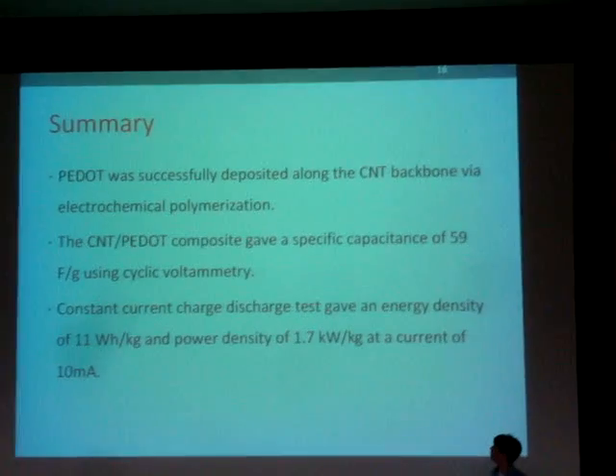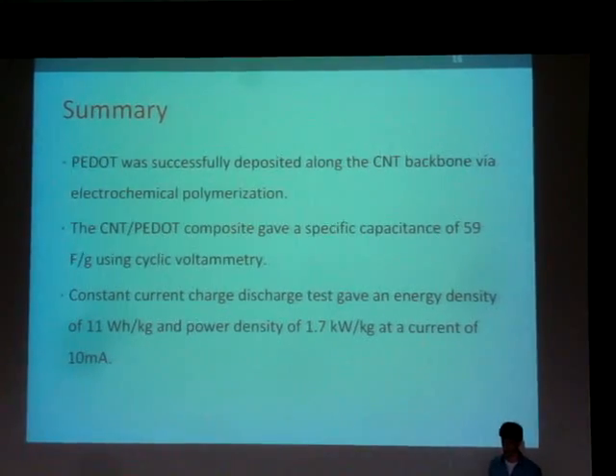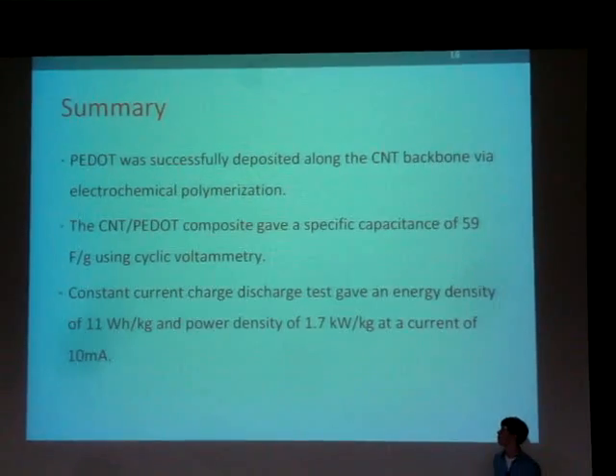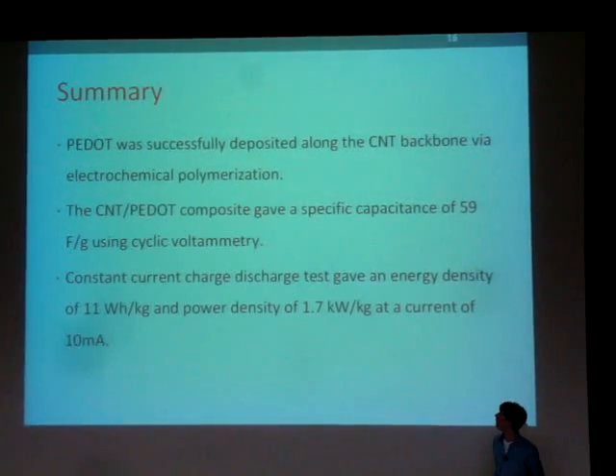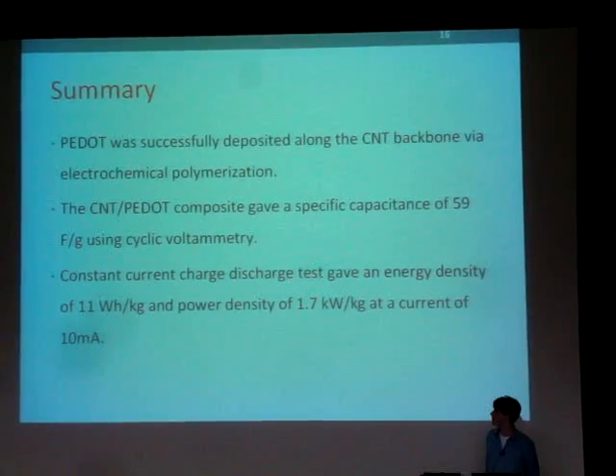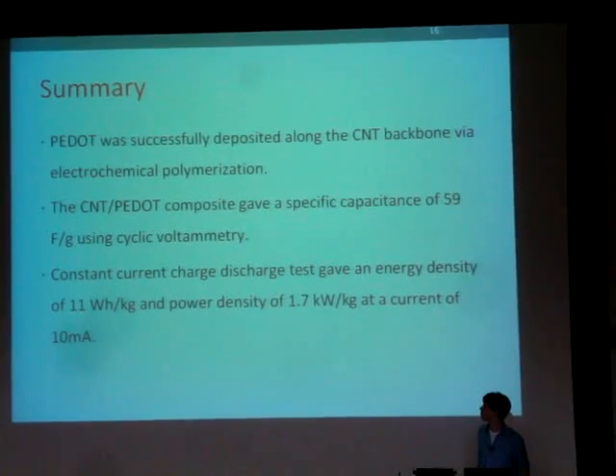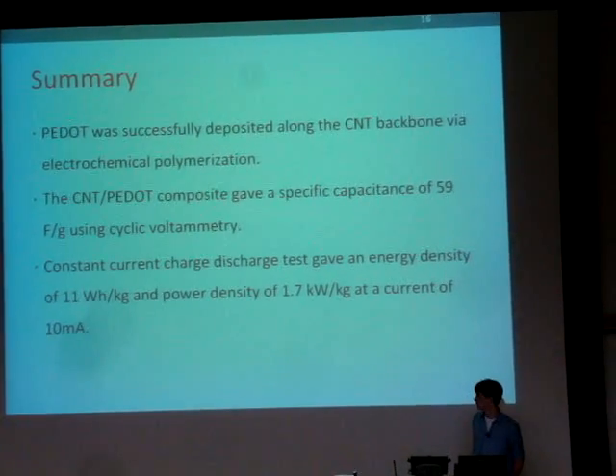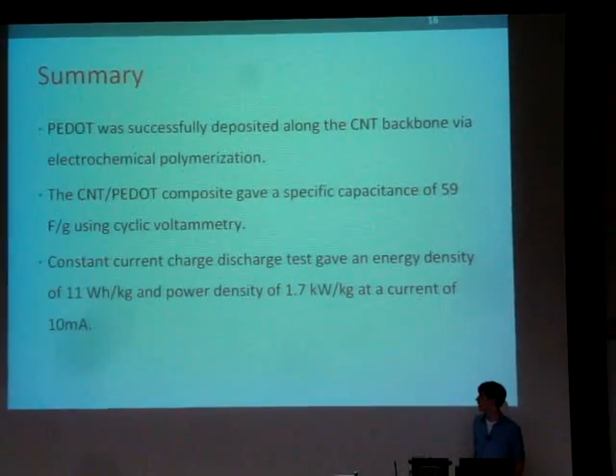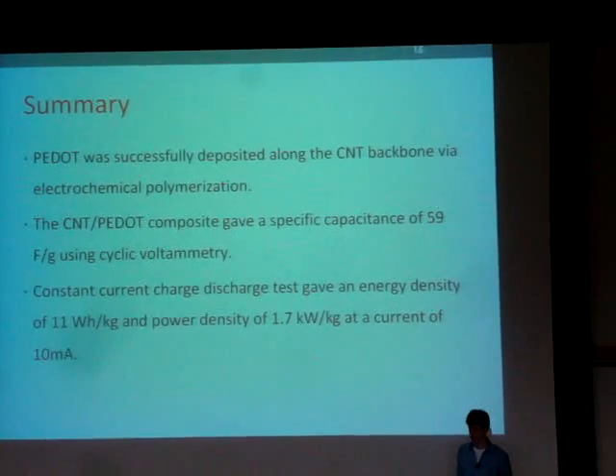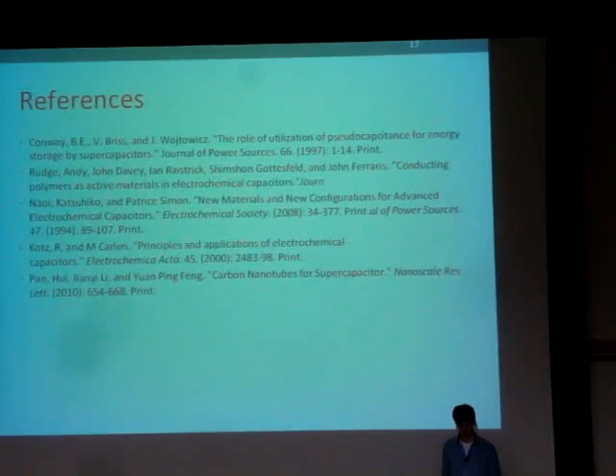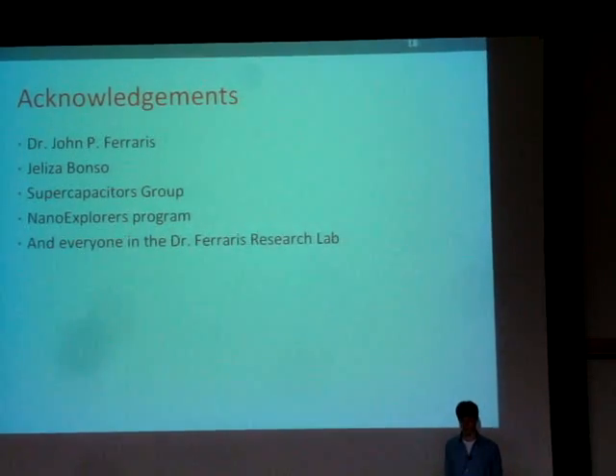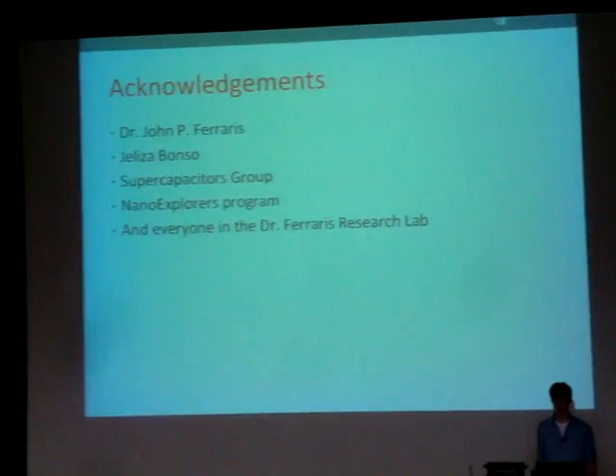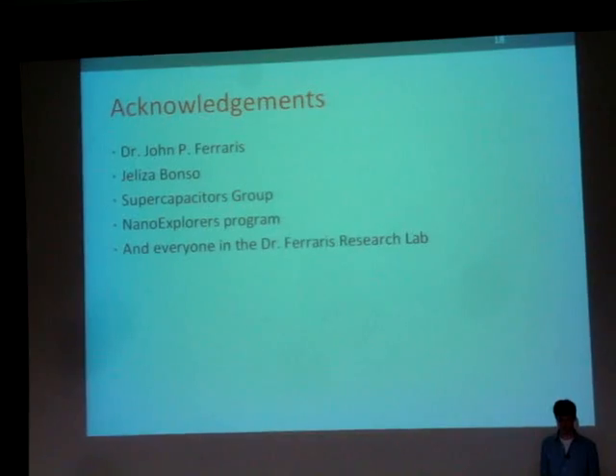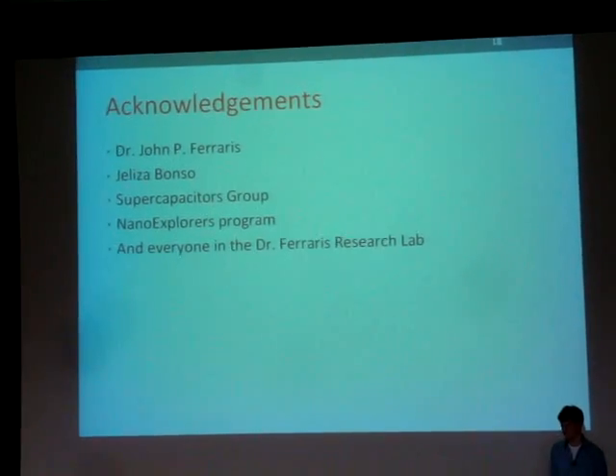So in summary, PEDOT was successfully electrodeposited onto the carbon nanotube backbone via electrochemical polymerization. The carbon nanotube composite gave us a specific capacitance of 59 farads per gram, and constant current charge-discharge test gave us an energy density of 11 watt-hours per kilogram, and a power density of 1.7 kilowatts per kilogram at a current of 10 milliamps. And I'd like to thank Dr. John P. Ferraris, my mentor Jaleesa Bonzo, the Supercapacitors Group, the Nano Explorers Program, and everyone in the Dr. Ferraris Research Lab.